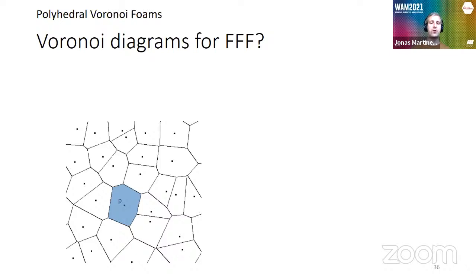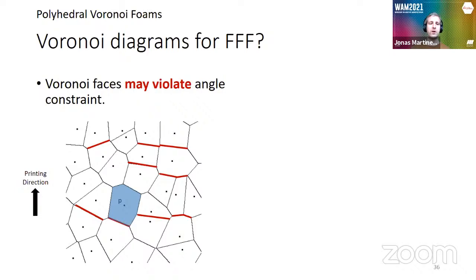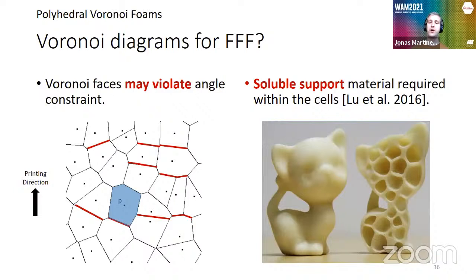Again, this is a set of points that is close to P, and it gives a partition of the space. However, if you look at some edges of this diagram, you will see that some of them actually violate the angle constraint. That is, with respect to the printing direction, the relative angle is greater than 45. Some previous work has used Voronoi diagrams, but they needed to use soluble supports in the interior. And we completely discard that because we wanted to scale, and this is quite tedious to remove.